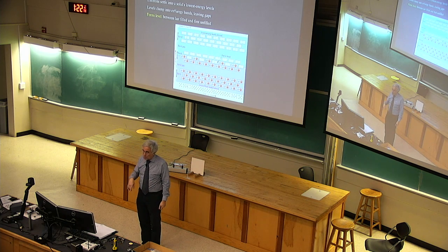So turning to this: if you've got a solid and you filled all the levels in the bands with electrons, and you try to get those electrons to rearrange, they can't do it. Not without a big investment of energy. Why? Because all the levels with similar energies are full, and the Pauli exclusion principle forbids you from piling extras in.